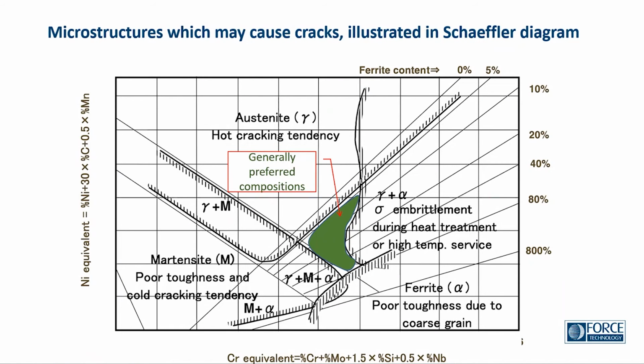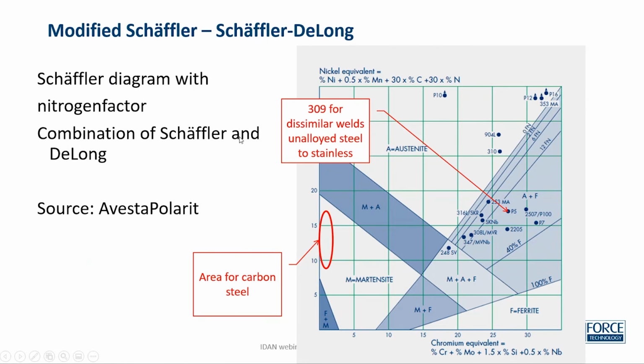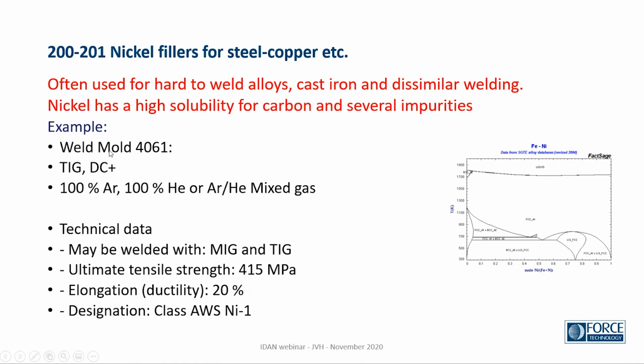But that can be handled by the groove design and the weld process itself. An example here is a filler called 4061, welded with TIG, with argon or helium or mixtures of those as shielding gas. We can use MIG or TIG to weld it, and we get strength at this level. So that's a filler material which can be used to solve some problems.